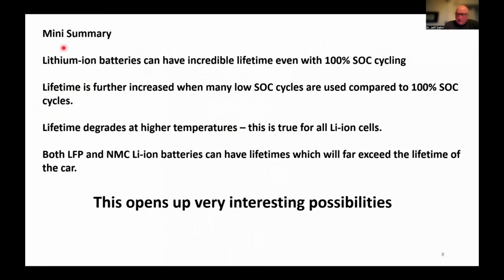So just a mini summary at this point. Lithium-ion batteries can have incredible lifetime, even with 100% state of charge cycling. And the lifetime is further increased when many low state of charge cycles are used compared to 100% state of charge cycles. And the lifetime degrades at higher temperatures, and this is true for all lithium-ion cells. But good lithium-ion cells, even at 40 degrees C, will have very, very long lifetime.